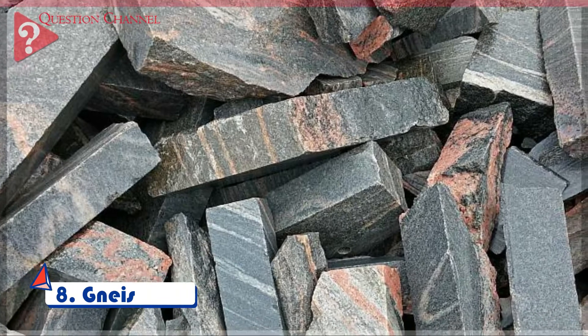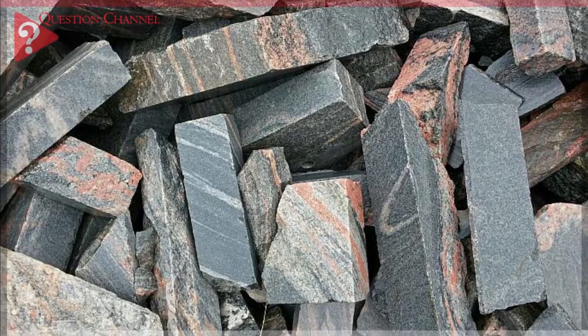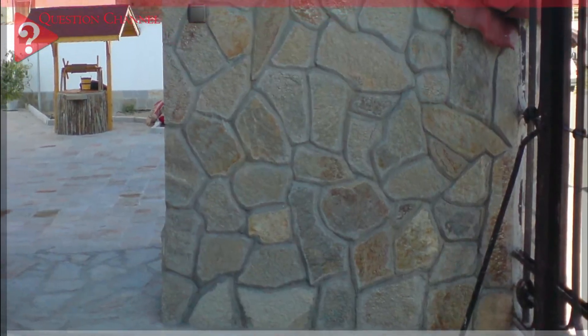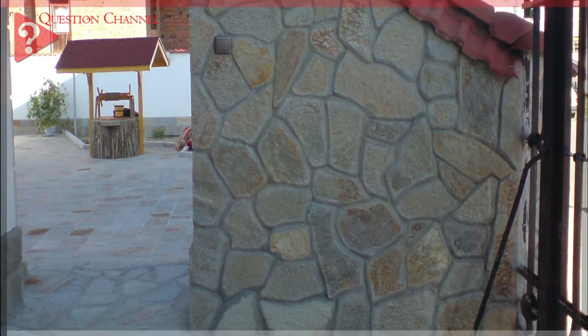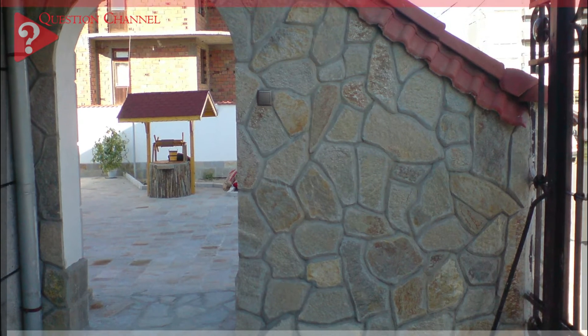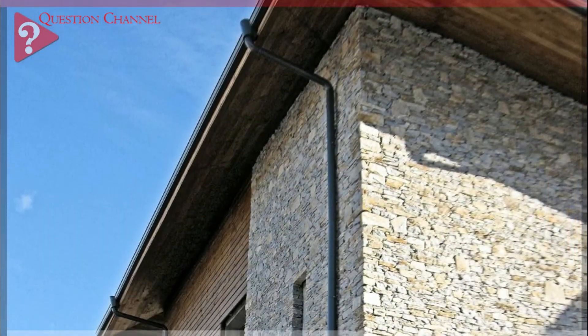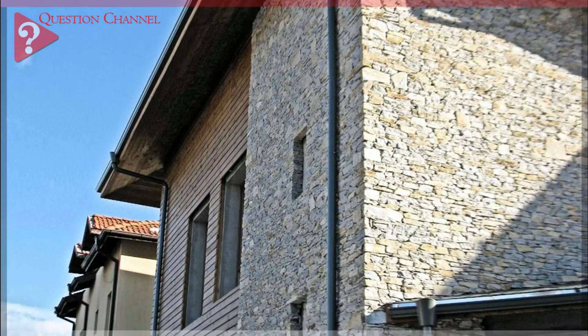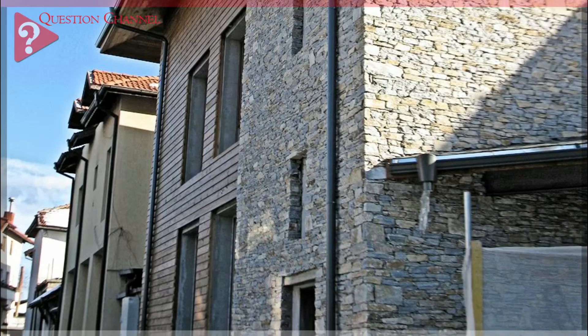Gneiss. This type of stone is used for minor construction since the presence of deleterious substances in its constituents makes it undesirable for building construction. However, hard varieties of gneiss stone may be employed in construction works. The compressive strength varies from 50 MPa to 200 MPa. It has fine to coarse grains, and its colour may be light grey, pink, purple, greenish grey, and dark grey.